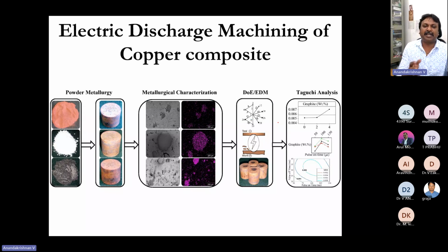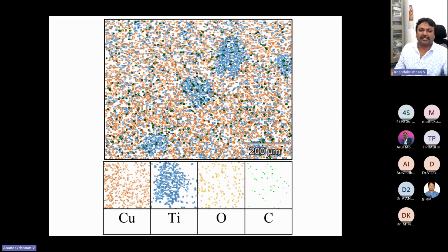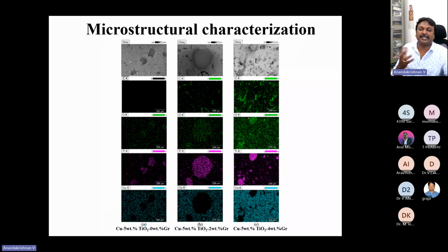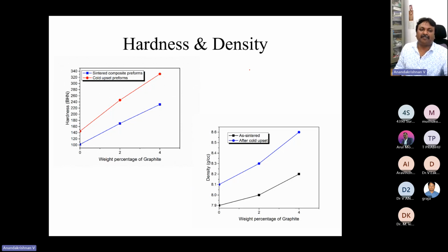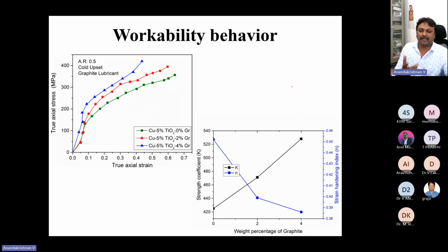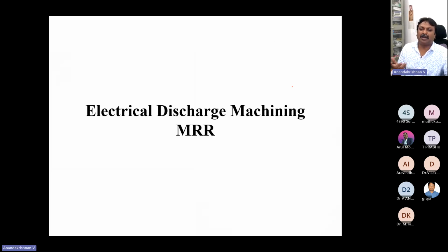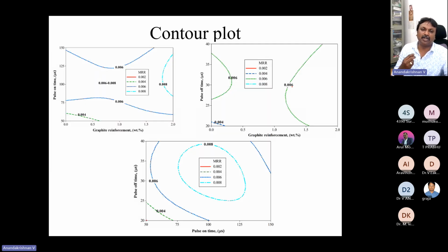Along with some of our research team, we have also done some powder-based compaction and sintering. We mixed copper, titanium oxide and graphite powders and created some components, and we analyzed them with scanning electron microscopy. Then we used them as electrodes for electric discharge machining. These are some of the evidences of metal matrix composites that have been made. We find a lot of property improvements when we include additional second phase particles, right? A lightweight particle is reinforced with a hard particle, high stiffness or high wear resistant, so that we can improve the workability or its endurance life.